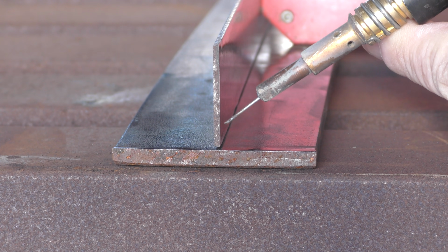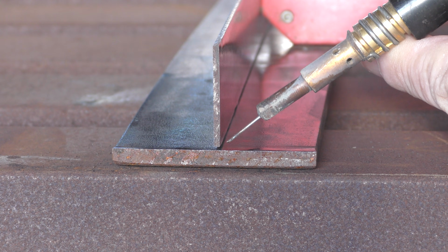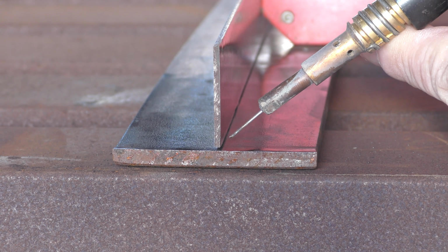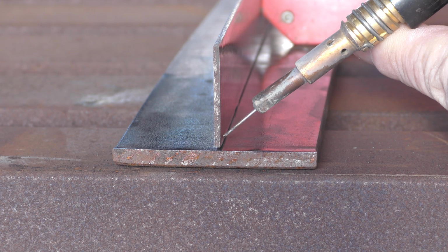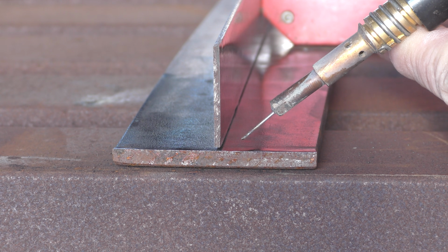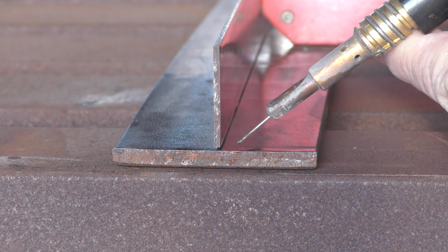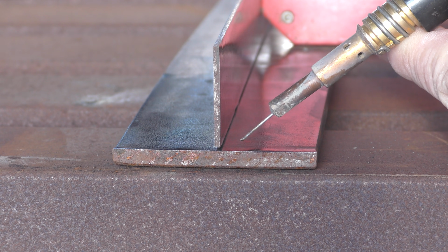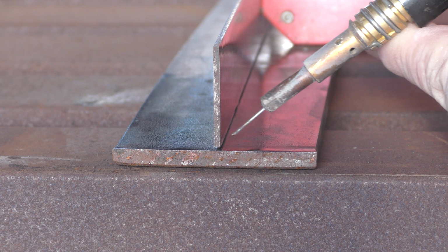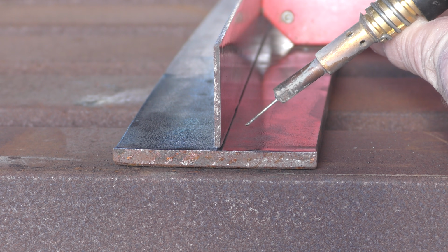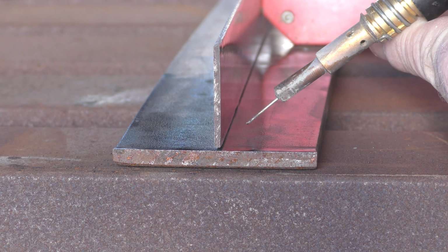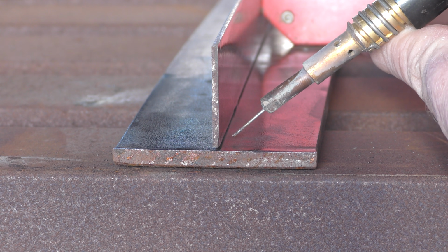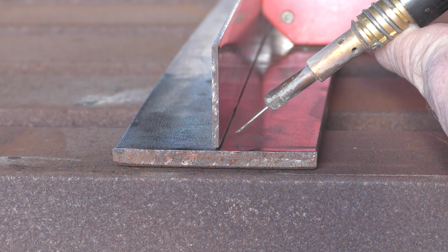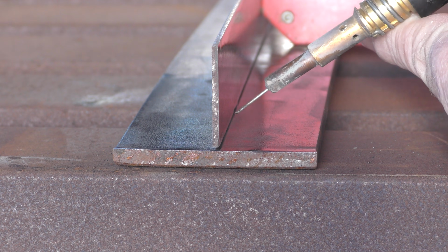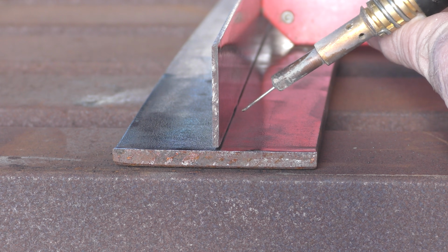Now, if the material that you're welding is going to be the same or similar thickness, you can focus your wire right here in the center so that each piece gets equal attention. But now, because we're welding something that's thicker, you want to pull back slightly so most of your attention is here on the thick, and as you start to run your bead, you just want to do quick bumps up, pause, up, pause, up, pause, up, pause. 75% of your heat is focused on the thick steel, with only 25% being brought up there quickly to the thin steel. So let me show you that in action.